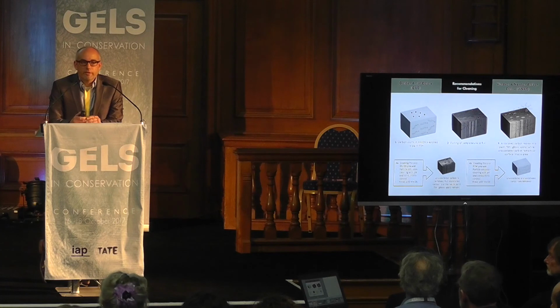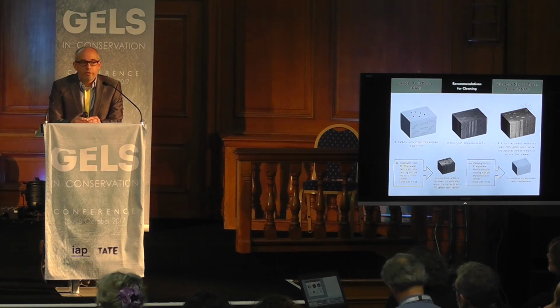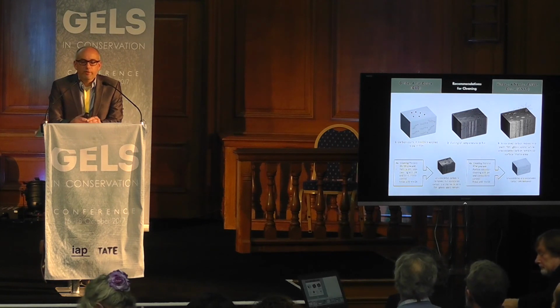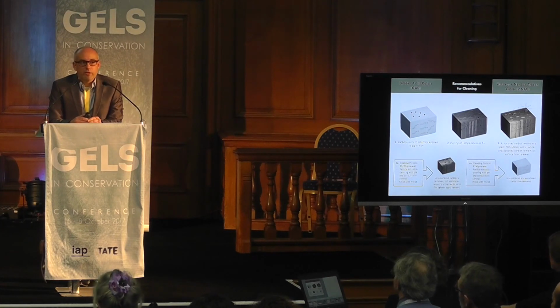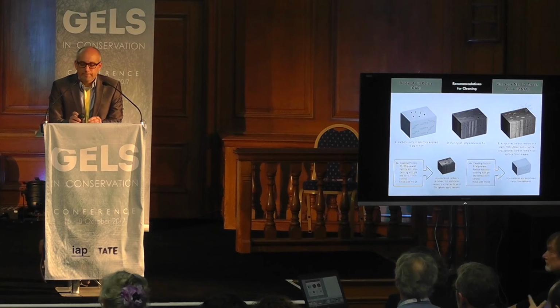In both cases, like everyone has done since we started this workshop, we're going to wet that surface with a cyclomethicone, a D4 or D5. We're going to make that cleaning system work hard to get at the surface, hold it back, build in some working time on these surfaces. We're going to build the cleaning system appropriate to the soiling mechanism and the surfactant. And then when we clear, we're going to rinse with D2. And then potentially in a few temperature or relative humidity cycles, we can get that gloss back and recover that.